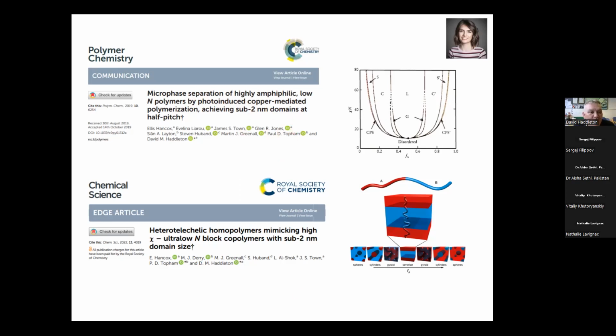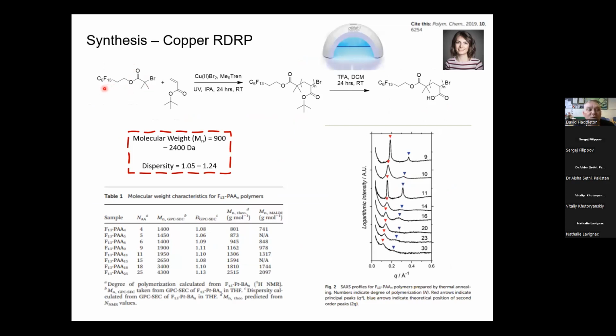Why are these so small? We've now got an initiator that's got a fluorine. So this is a discrete molecule, and we're going to change the length of that, change the amount of fluorine. We polymerize off using our UV system using copper-2. We use T-butyl acrylate, and we then hydrolyze to get acid. So we've got a fluorinated block, a discrete block, and we have an acid block. So these are very, very different in polarity.